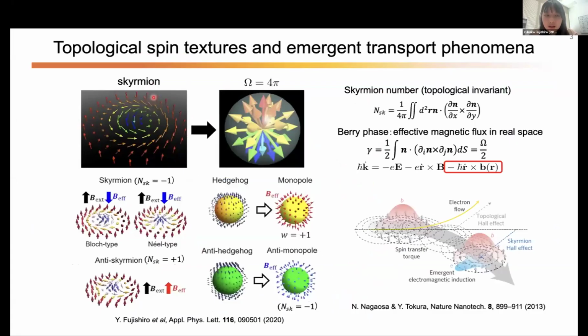The topological spin textures, as you may already know, are now found in various magnetic compounds. For example, the magnetic skyrmion has a spin texture like this. When we project these spin textures on a sphere, it actually overlaps one sphere surface and has a quantized solid angle. Depending on the crystal symmetry, we have various kinds of detailed winding patterns as shown here. The skyrmion is rather a two-dimensional spin texture, while the spin texture called hedgehog and anti-hedgehog lattice has a more three-dimensional nature.